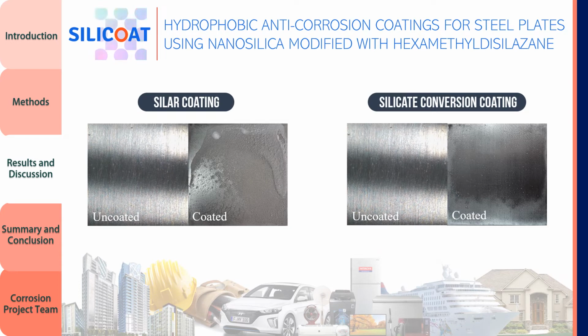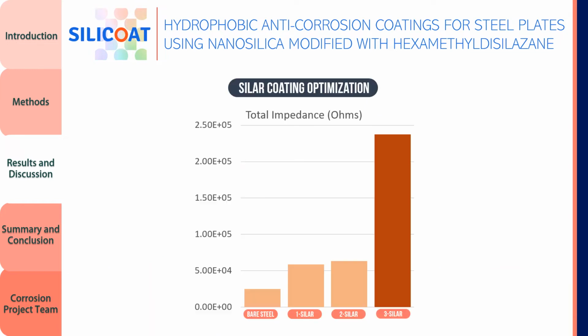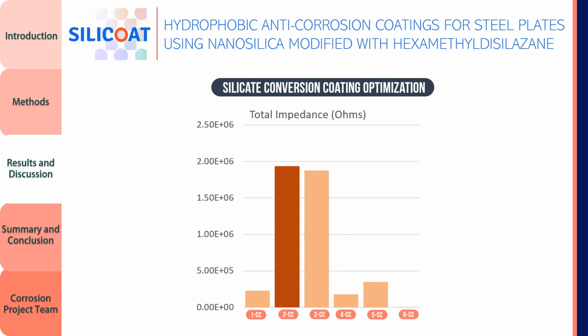On the left-hand side of this slide, the specimen coated using the SILAR technique is shown, while the specimen using the conversion coating is shown on the right-hand side. There were three formulas developed under the SILAR treatment of application. One of the formulas developed reached around 250,000 ohms of total impedance. This was marked as the optimum formula under SILAR. On the other hand, two of the formulas developed using conversion coating reached around 2 million ohms. The formula with a higher total impedance was marked as the optimum formula under conversion coating group.